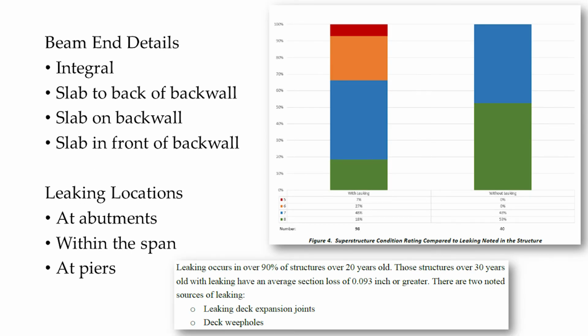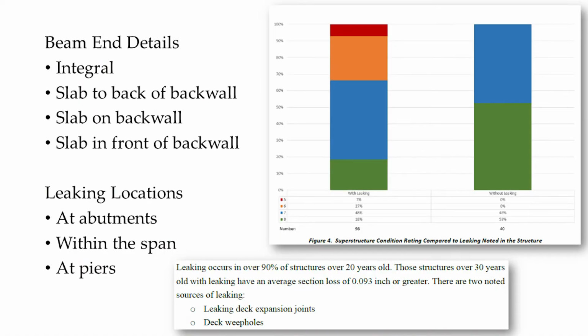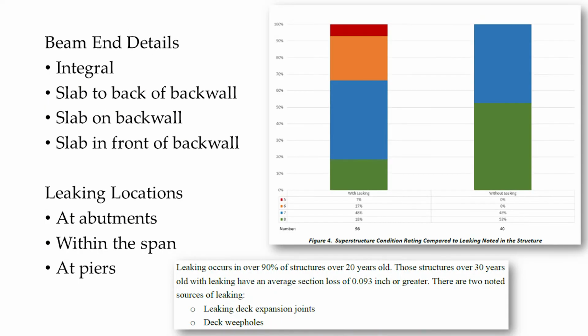They looked at various bridges, and the key thing they found was if there is leaking on the bridge, that has a significant impact on the performance. Of the bridges in the study, 98 on the left of them had leaking, 40 on the right with no leaking, much better performance. These numbers are ratings. So you have some 5s, which are the dark orange, and 6s, which are the lighter orange, on the leaking side. On the bridges without leaking, nothing worse than a 7.